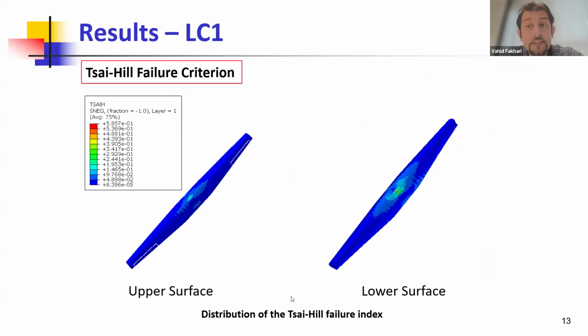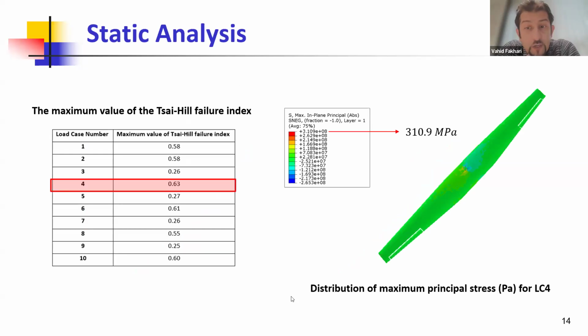Also, in this study, the Tsai-Hill failure criterion was employed for strength evaluation of the composite wing structure. This figure indicates the distribution of the Tsai-Hill failure index on the upper and lower surface of the wing structure. A value greater than 1 indicates failure. This table shows the maximum value of the Tsai-Hill failure index for all peak load cases. All values are lower than 1, which means that the wing structure had sufficient strength in the presence of the applied aerodynamic loads. However, load case 4 has the highest value.